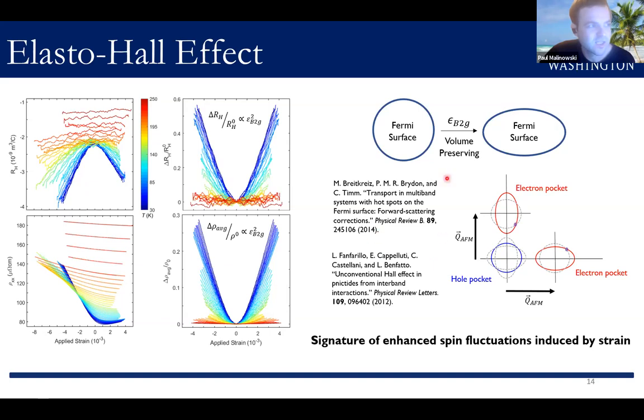Although if these theoretical works are correct, which it seems like our data is consistent with, then the Hall coefficient is not simply interpretable in terms of a multi-band situation. These results that they derive actually represent a failure of the Boltzmann transport. It's beyond the simple multi-band formula, because if you just look at the numbers, this would suggest that the carrier density is changing by a lot.